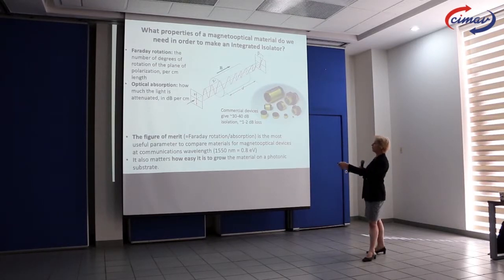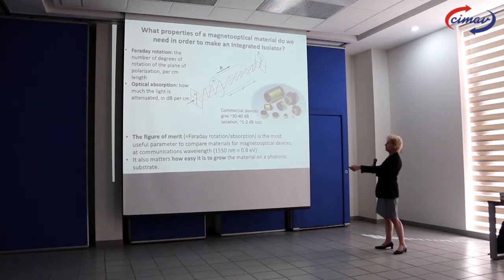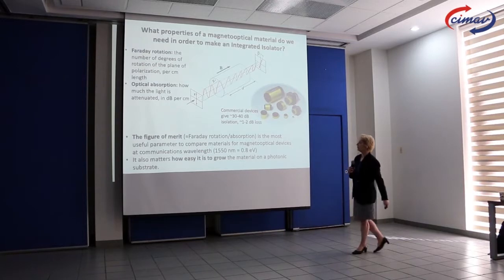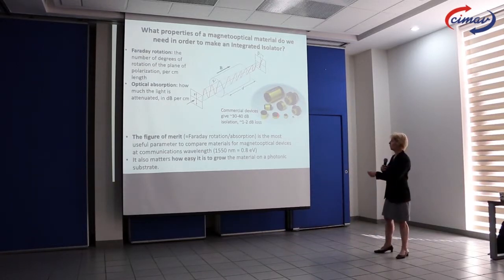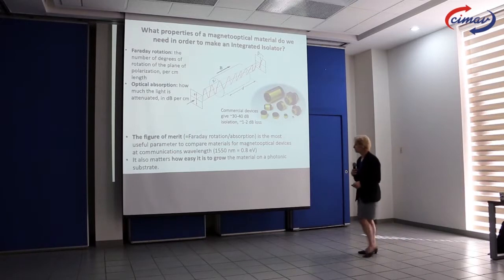So the direction of rotation depends on the direction of magnetization. So if I send light through, it gets rotated by 45 degrees. If the light comes back again, it goes through another 45 degrees in the same direction, and now it's in this direction, so it gets blocked by the initial polarizer. So that's how an optical diode works. What's inside these things is two polarizers, one crystal of garnet, and a magnet. That's all there is inside them.